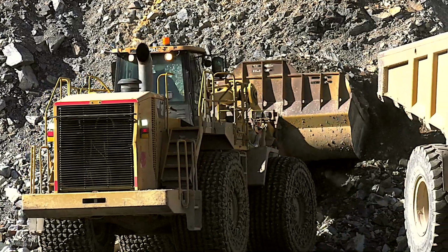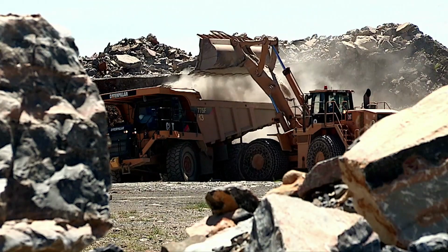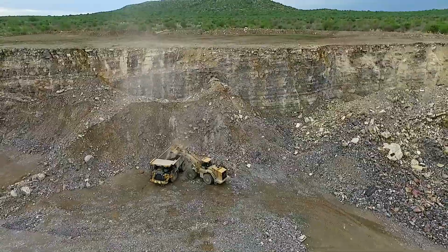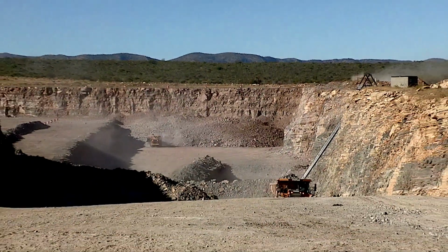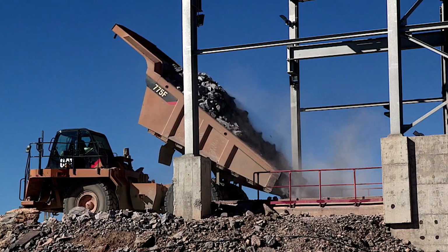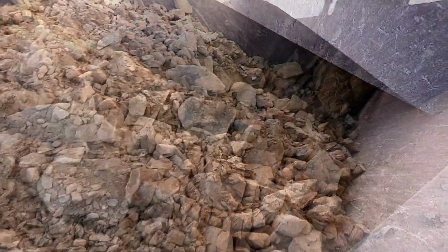The most important raw materials for the production of cement are limestone, shale and marl, which are available in large quantities in the quarries of OHORONGO. The other ingredients such as iron ore and gypsum are obtained from local Namibian mines, supporting the growth-at-home policy of the Namibian government. The limestone, shale and marl is loaded onto haul trucks with a loading capacity of 60 tons each. These raw ingredients are transported in specified ratios to the crusher, where they are ground to the consistency of rough gravel. The crusher can handle 600 tons of raw materials per hour.